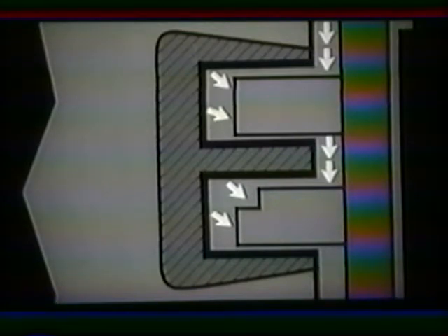Because of this design, we obtain the greatest sealing force when the gas pressure is greatest, during the power stroke. This flexing and sealing of rings results in a high wear situation for both the rings and the grooves in which they sit. For this reason, the face of the compression ring is chrome-plated and polished to a smooth finish. Rings used in hot applications are coated with molybdenum, which has lubricating properties of its own to minimize scuffing.